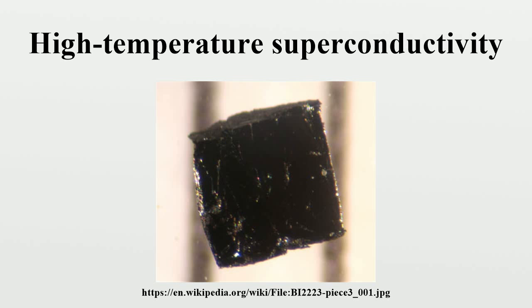The preparation of Bi-, Tl- and Hg-based high Tc superconductors is difficult compared to YBCO. Problems in these superconductors arise because of the existence of three or more phases having a similar layered structure. Thus, syntactic intergrowth and defects such as stacking faults occur during synthesis and it becomes difficult to isolate a single superconducting phase. For Bi-Sr-Ca-Cu-O, it is relatively simple to prepare the Bi-2212 phase, whereas it is very difficult to prepare a single phase of Bi-2223.